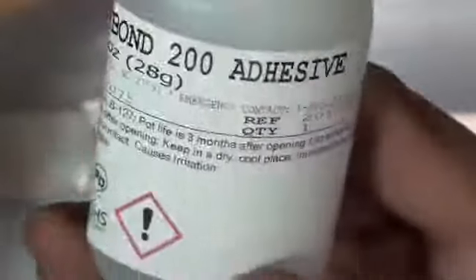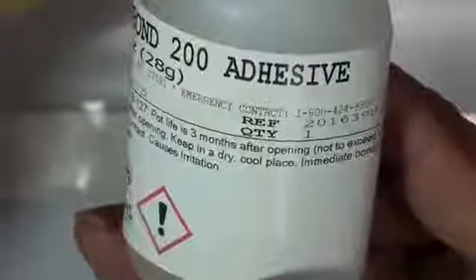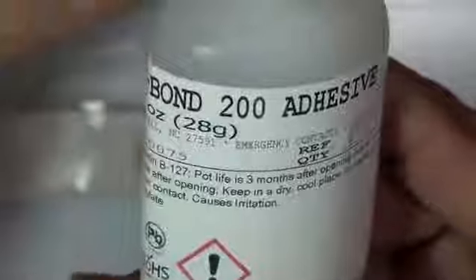So just keep in mind when you're using this catalyst, it's not something that gets mixed liquid to liquid with the adhesive. It's allowed to dry, so we usually give it at least 60 seconds to make sure that it's completely dried before we apply the adhesive. The adhesive that we're going to use here is M-Bond 200. This is a cyanoacrylate instant curing adhesive. Sometimes people generically refer to this family of adhesives as a super glue.